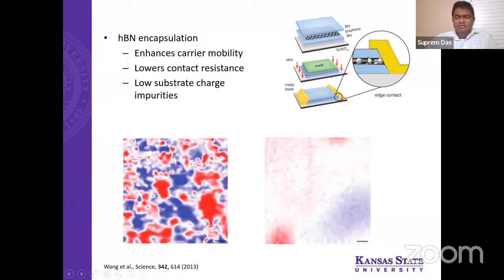But the lattice constant, since it is similar, you can have so-called epitaxial layer. And as we know, if things become epitaxial, then you can substantially increase the mobility. Now that's exactly what happens. If you can really make ultra clean, this kind of epitaxial layer with the 1D contacts, then you can have very high mobility. And in this paper, for the first time, they showed that this configuration can give you very high mobility.